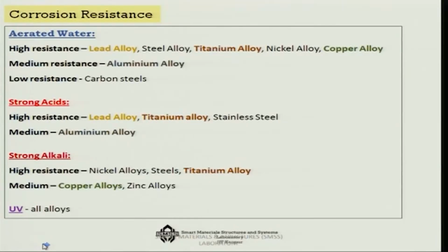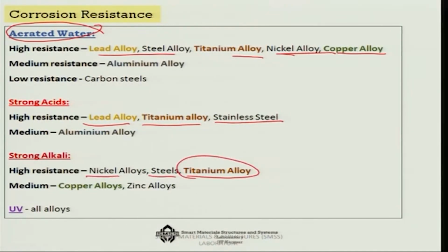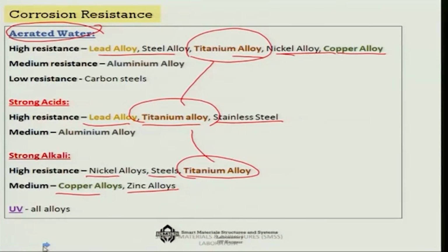Now, in terms of corrosion resistance, for aerated water, it is the environment which is important. Lead alloy, steel alloy, titanium alloy, nickel alloy, copper alloy, all of them give high resistance, but aluminum alloy does not. Low resistance is particularly seen in carbon steels. In a strong acidic medium, you will see titanium alloy, lead alloy or stainless steel perform well; aluminum alloy is medium. If it is strong alkaline, nickel alloy, steel and titanium alloy are good, and medium is copper alloy and zinc alloy. For UV, generally all alloys. So, one common thing we can see is that no matter what the medium, titanium alloy is good in most corrosive environments. That is why it is heavily used for corrosive environments.